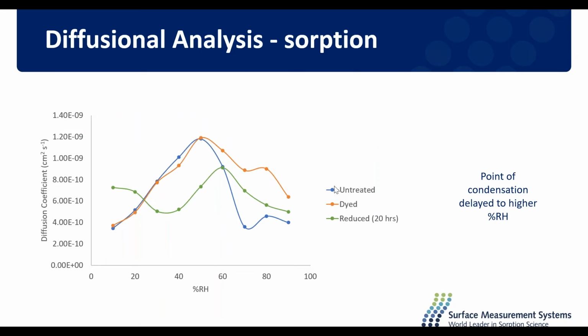So how has this changed for our damaged hair samples? Well, we can see the untreated hair in blue here, dyed hair in orange, and our reduced hair in green. And we can see that there is definitely a difference going on here. We can observe that the point of condensation, that maxima, has shifted along for our reduced hair sample, and the diffusion coefficient has remained high for our dyed hair sample.